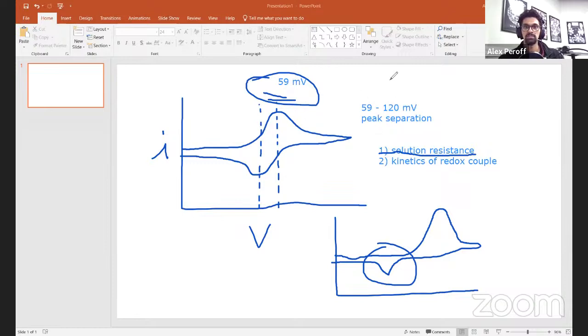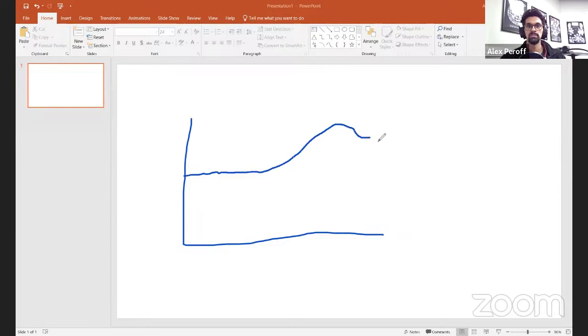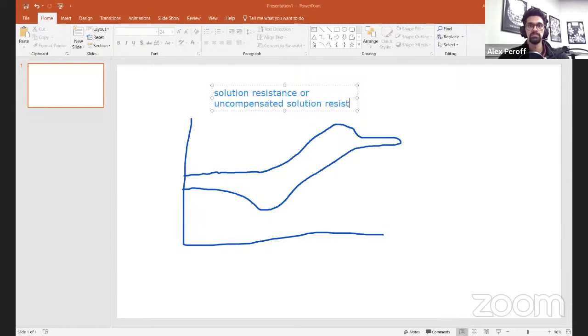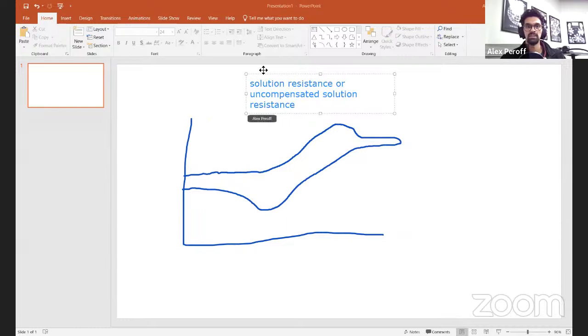But the kinetics is one reason why you see this change in the peak separation. The last thing I want to mention is about the solution resistance. I made a video about this, about IR compensation, that you can get these elongated voltammograms that are kind of stretched. They look a little bit more like this. And this is when solution resistance is high or not compensated for, uncompensated solution resistance. So this is how you can get these kind of big peak separations. And yeah, in the literature, you might not find people who actually talk about it.